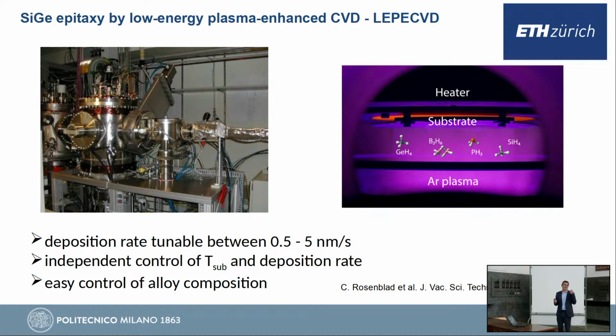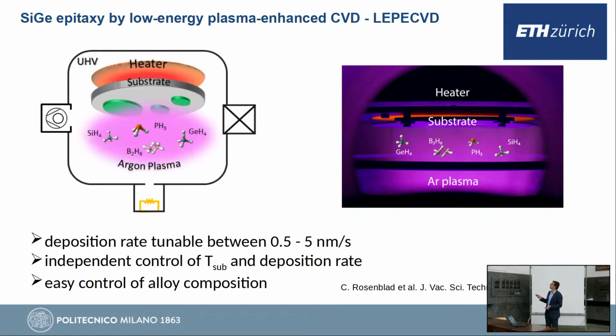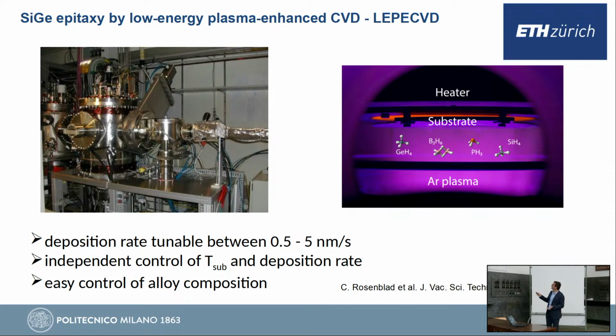It means that the silicon and germanium atoms, before becoming solid and being incorporated on the sample surface, are in a gas phase. So we use these gases, like silane, which is silicon, and this, again, this tetragonal bond is filled by 4 hydrogen atoms. Germane, which is the same thing. Methane, which we all know is the same carbon with 4 coordinated hydrogen atoms. So everything happens in vacuum. So as many deposition systems, this looks like a chunk of stainless steel, which is pumped out to obtain vacuum.